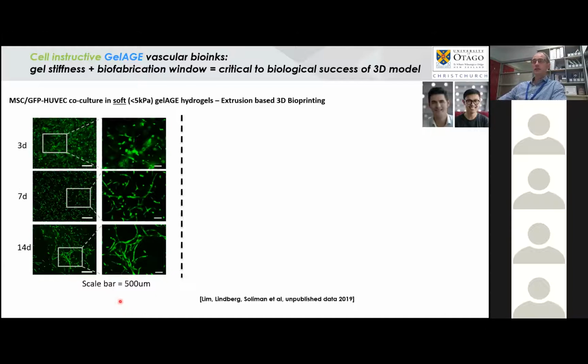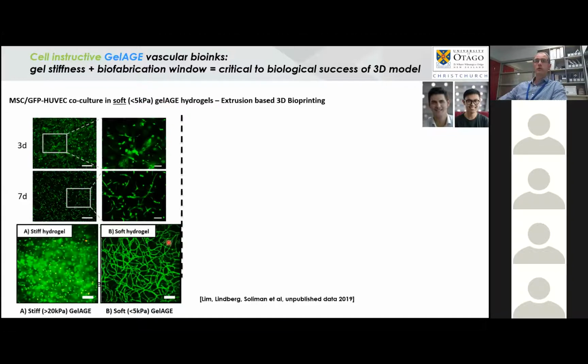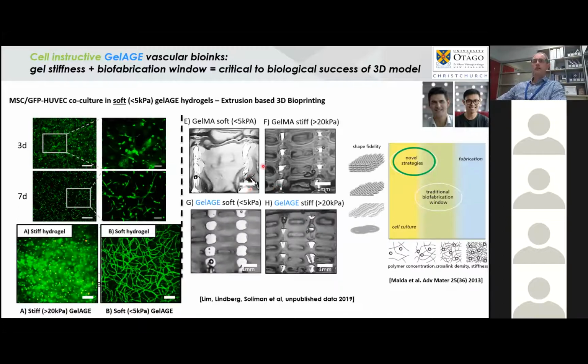What does that mean in terms of the structures we can try to fabricate? Well, for vascular-based bioinks, what we would like is very soft, permissive hydrogels to allow network formation. What we know is that you get network formation in soft hydrogels generally below 5 kPa. If you have a hydrogel above 20 kPa, you don't end up with a permissive microenvironment, as seen with a co-culture of mesenchymal stromal cells and GFP-labeled HUVECs. So if you would like to generate a soft permissive hydrogel, you can't achieve any sort of print resolution with GelMA because it doesn't have the right rheological profile.